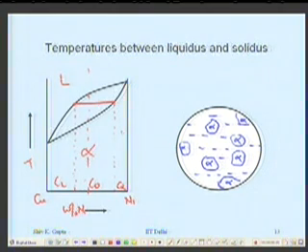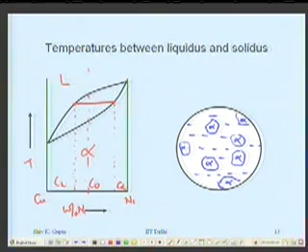That's how the microstructure will look. Look at the crucible. This is how the system will look. Some particles of solid floating with the composition here, and the liquid with the composition there. And this situation shall go on till I cool down to the solidus. But the amount of solid will keep on increasing. The amount of solid was 0 just at the liquidus, and it shall keep on increasing as I go down, and it shall become all solid by the time I reach solidus.